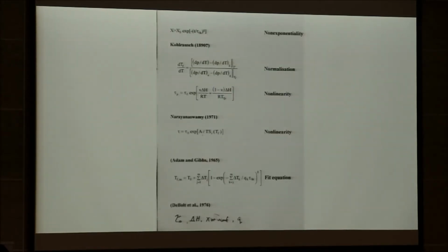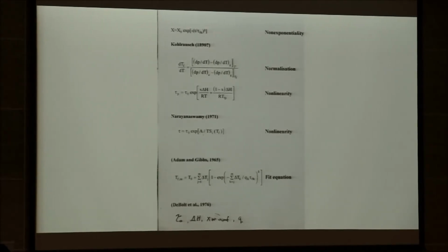Maybe one word for those who are interested. There are two major issues in this kind of measurement. There is the non-exponentiality of relaxation. I'll just say it for those who might know, and ignore it for those who don't know what that means. It means that the relaxation curve as a function of time is not fitted to a simple single relaxation time or an exponential decay. And we've known that since about 1890. And the other thing is it's a nonlinear process, because as I heat the sample up in the calorimeter, the target that the relaxation is trying to go towards is a moving target, because the temperature is changing, and the equilibrium state changes as a function of temperature. So this is why these curves look a little bit weird. You're dealing with nonlinearity and non-exponentiality at the same time, okay?